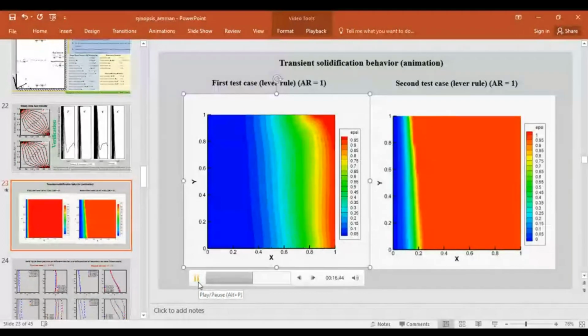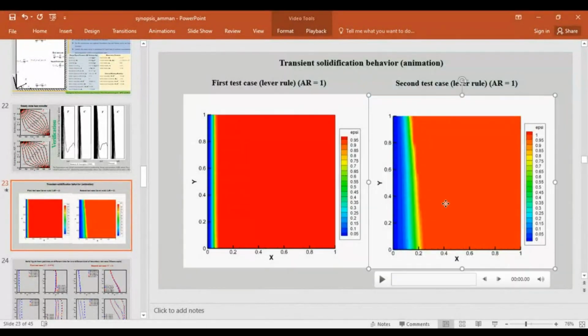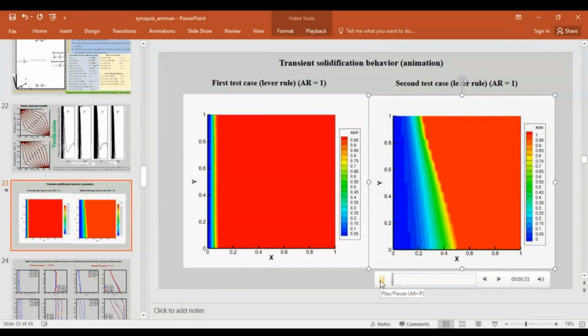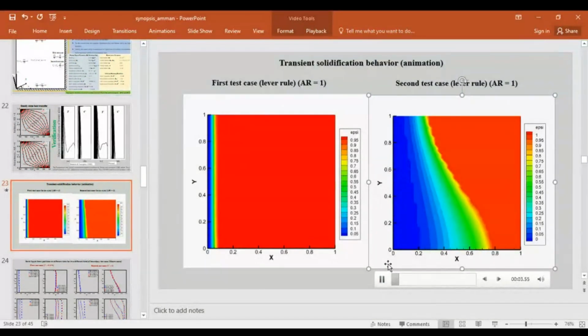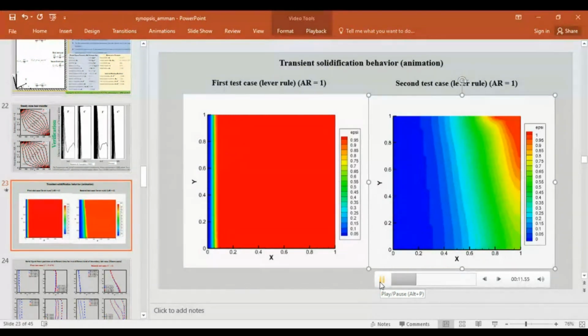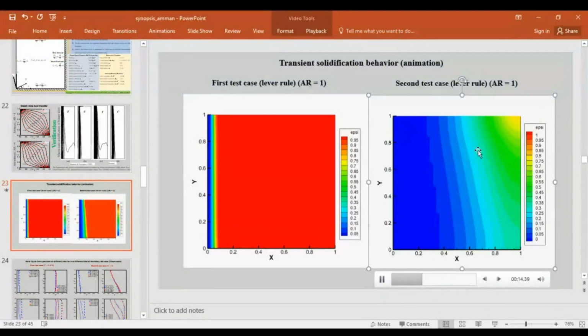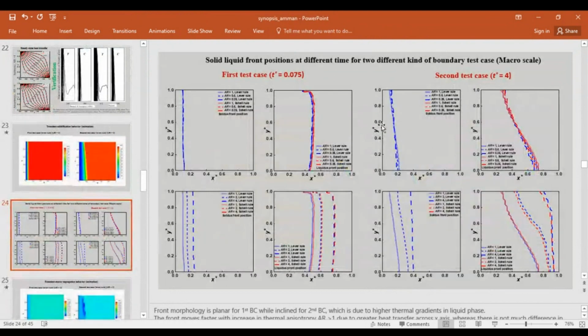But for the second case where AR equals 4, the solidification is much faster, you see. The solidification takes very less time here. Why? Because the thermal conductivity is higher along the X direction in the solid phase. So here, to do a more effective comparison, the solid-liquid front position at different times has been plotted for the first test case and the second test case.